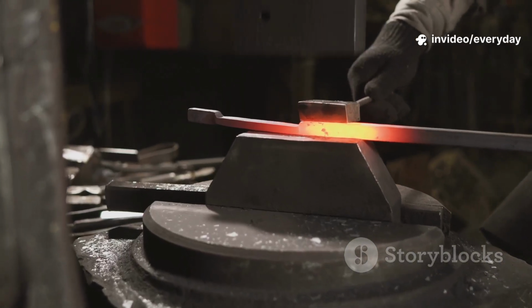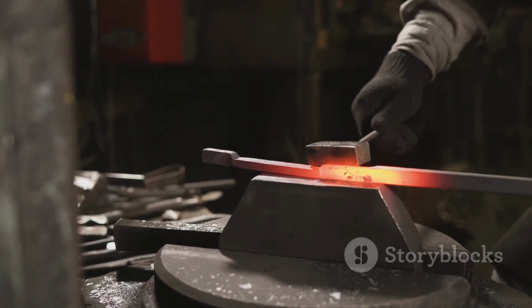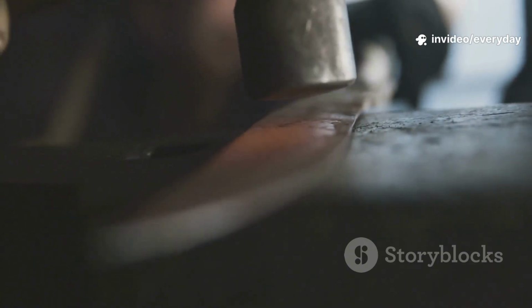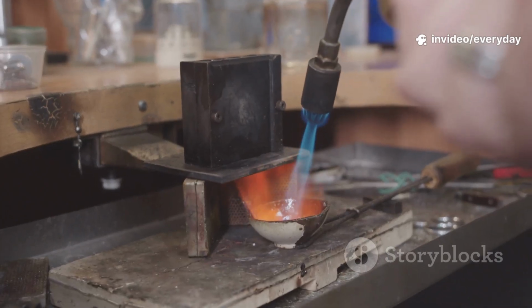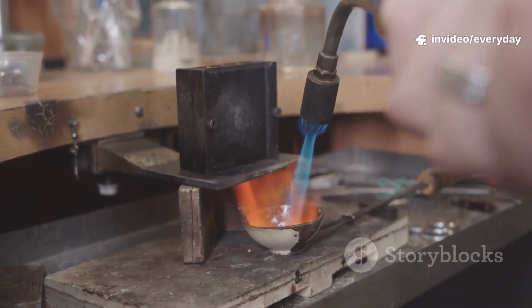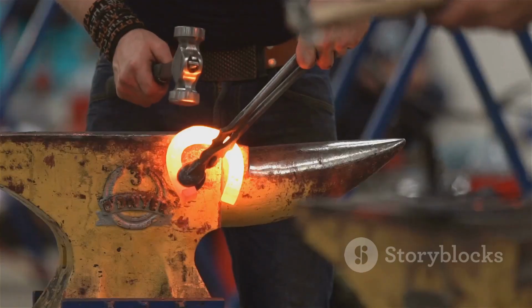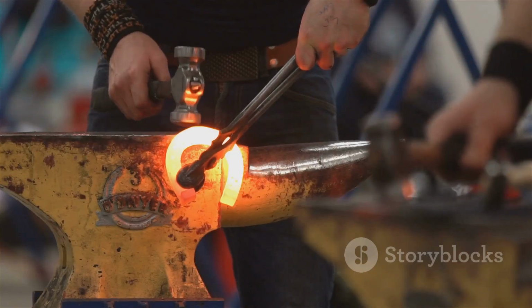Temper between 350 and 500. 400 is a strong starting point. Run two 2-hour cycles, cooling fully between them. Tempering precipitates carbon, relieves stress, and adds toughness. With a torch, chase temper colors. Light straw to bronze for knife edges. Keep heat moving. Localized overheating softens the blade.